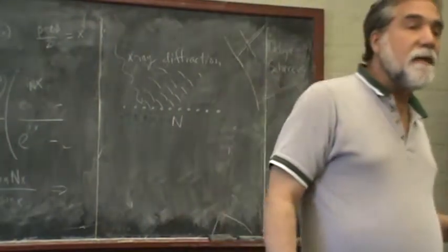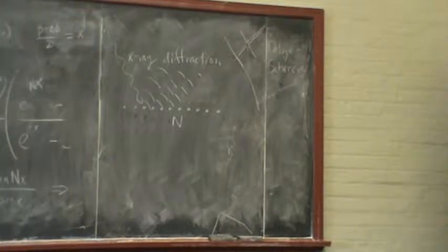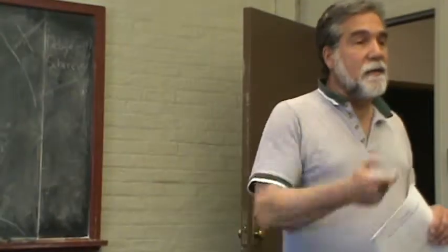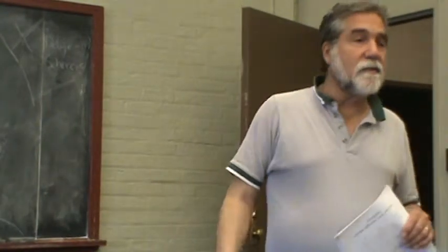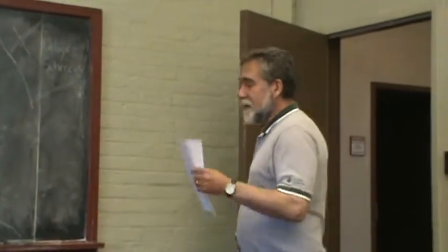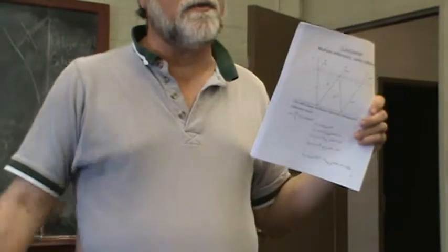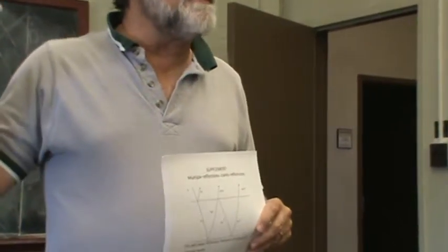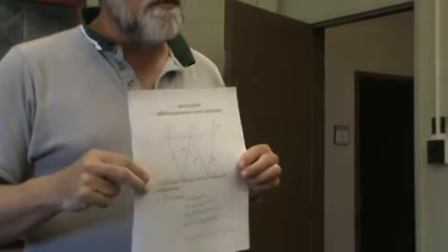You can measure the size of your nanocrystal, for example, by just measuring the width of the diffraction peak that you see from that. Right? But wait, there's more. So X-ray diffraction, we just did it, right? That same arithmetic that I just did here is what's used in multiple beam reflection.